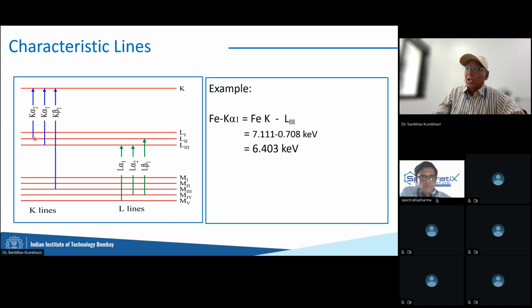But if it is an L2 line that jumped, it becomes K alpha 2. And if it is L1, it is K alpha 3. But that doesn't happen. That distance is too close. Those energies are not relevant. Only either of these two always happen. Sometimes something from M also jumps to K, and then we call it a beta: K beta 1, K beta 2, K beta 3, and so on and so forth.